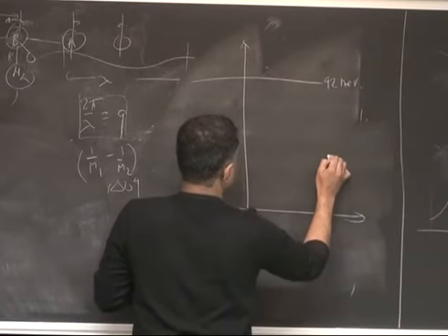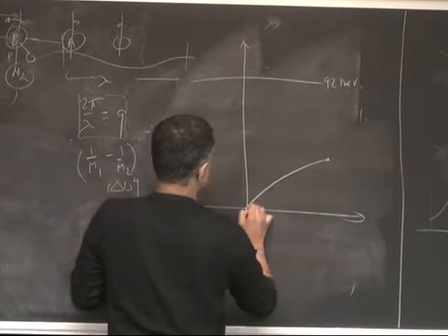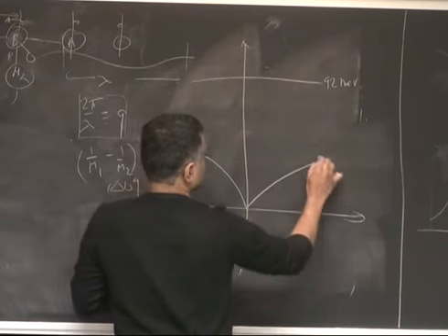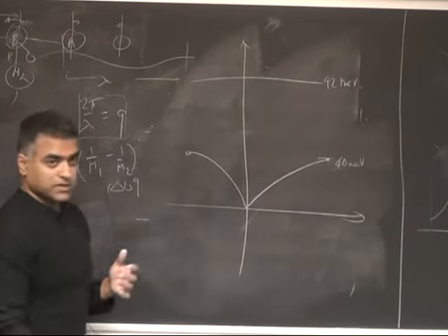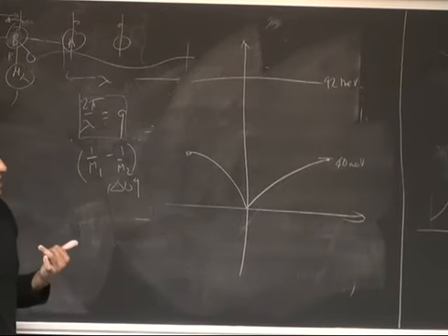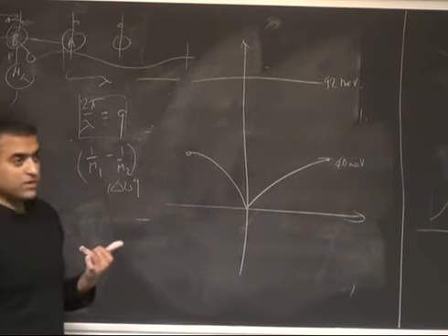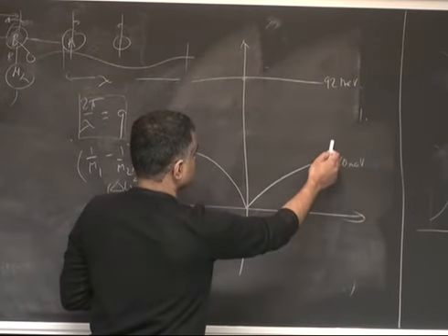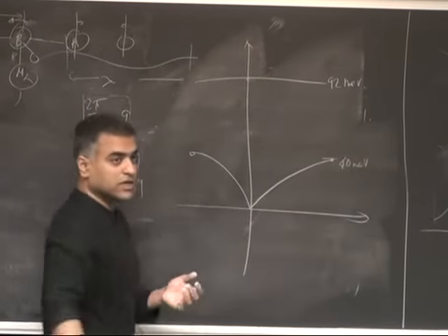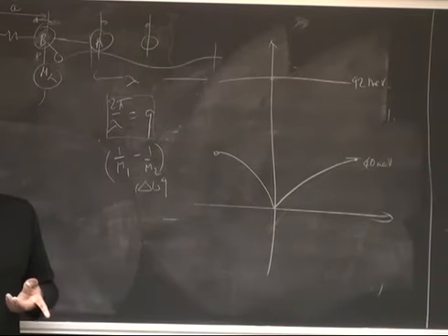But the maximum of the acoustic modes is close to 40 meV. That's the max, right? So you see, you don't have the Klemens channel here at all. You can't decay; 92 divided by 2 is 46. You can't go to acoustic modes. It's blocked. Right? Does that make sense?